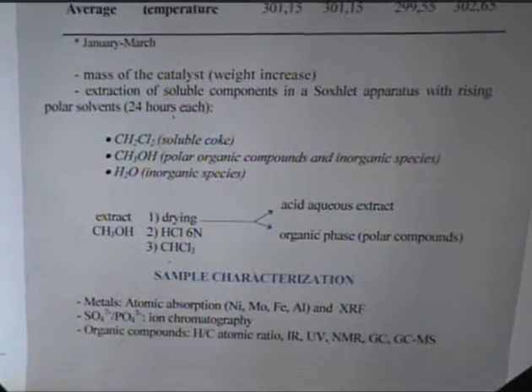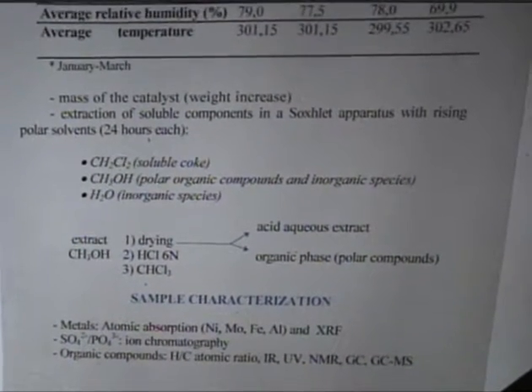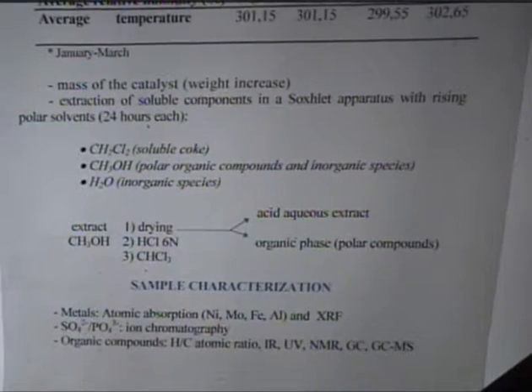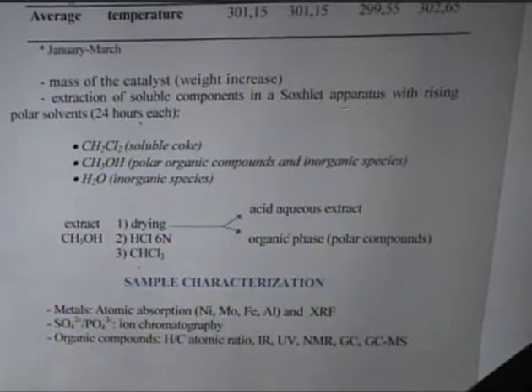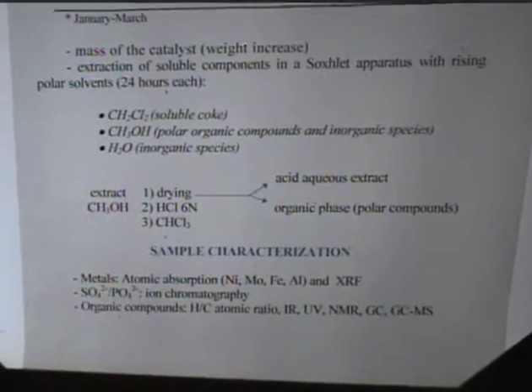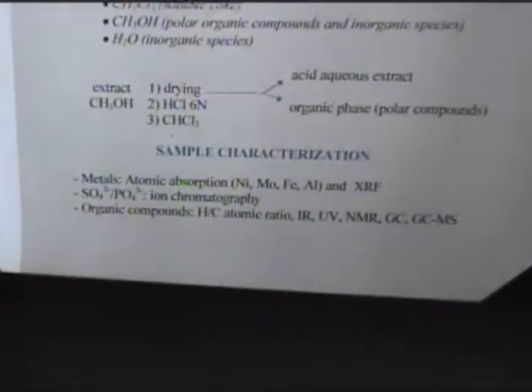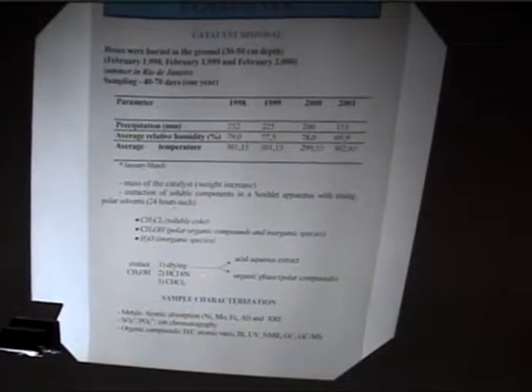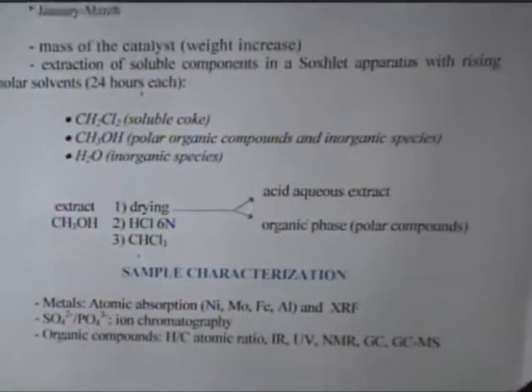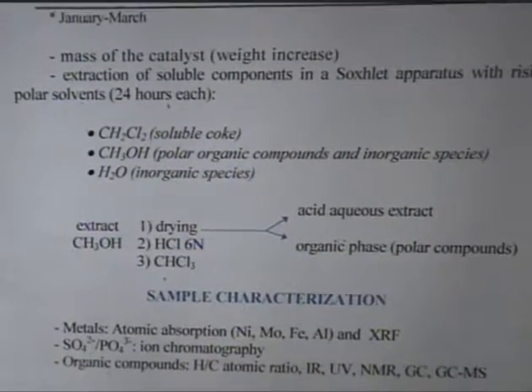After sampling, the catalyst was weighed in order to determine its gain of weight, and it was submitted to an extraction procedure of soluble compounds in a traditional Soxhlet apparatus using solvents in rising polar order. Dichloromethane for the ordinary soluble coke, methanol for more polar organic compounds and some inorganic species, and finally water to solubilize some inorganic species. Methanol was first eliminated under vacuum, after which the residue was dissolved in dilute hydrochloric acid, and the polar organic compounds present were extracted with chloroform. All organic and inorganic species were characterized by means of the traditional analytical methods.